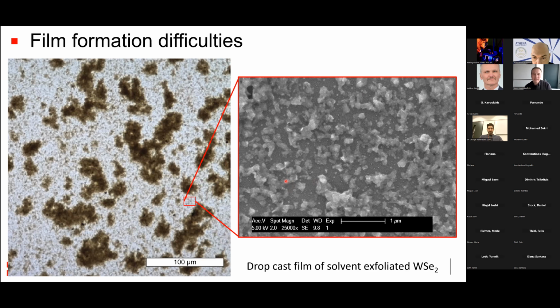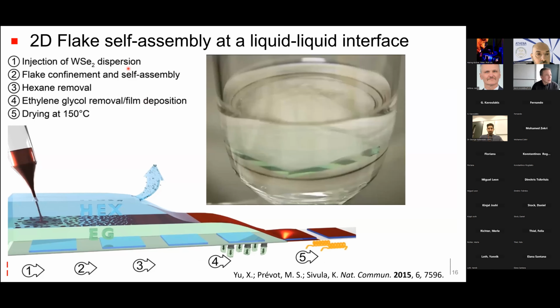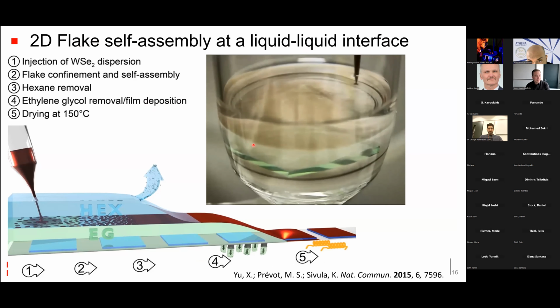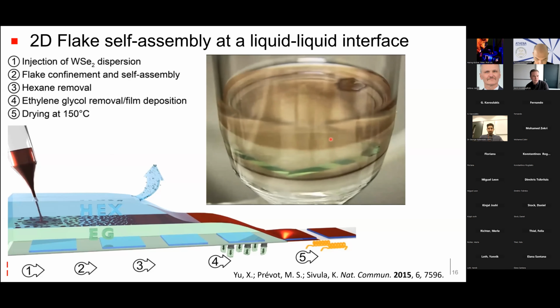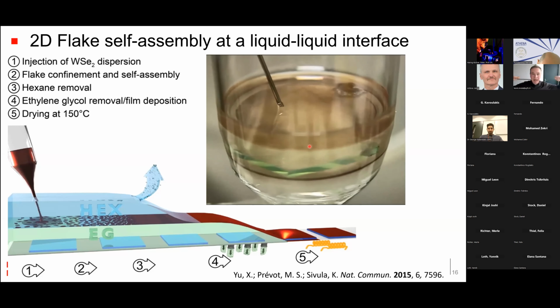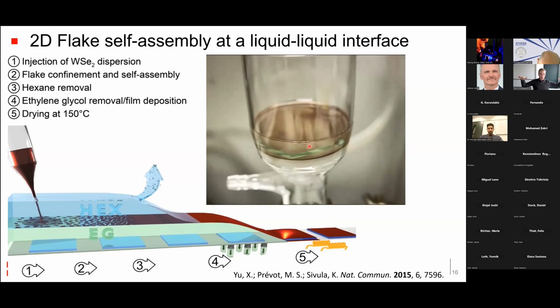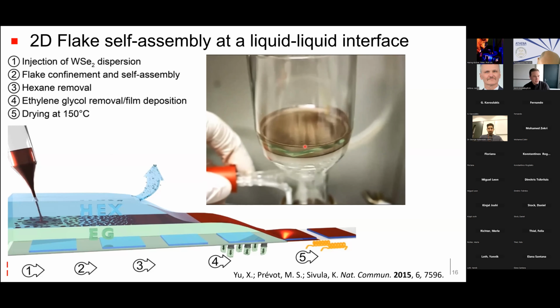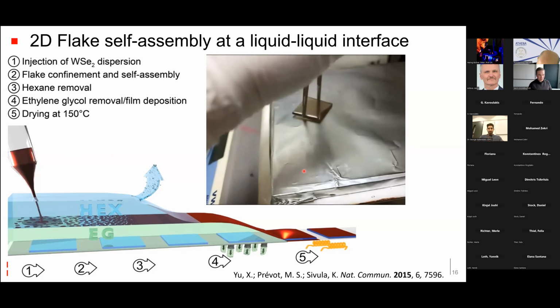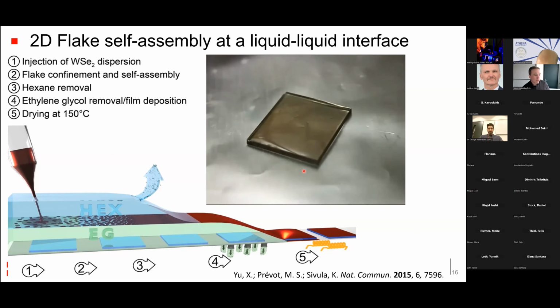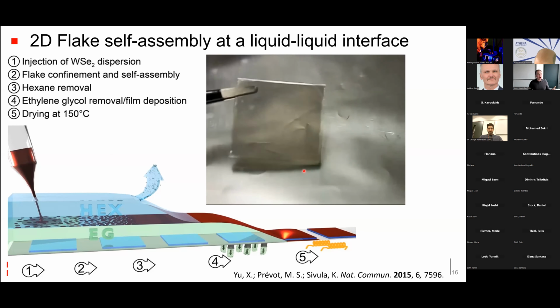But I had a very brilliant PhD student who figured out that we could use flake self-assembly at a liquid-liquid interface. So I'll just show you a video here quickly. We inject the dispersion of the nanoflakes at an interface, for example, of hexane and ethylene glycol. And since our solvent here, NMP, is soluble both in hexane and ethylene glycol, the solvent goes quickly into those phases, leaving the nanoflakes to minimize their energy and align at that liquid-liquid interface quickly. Then we can simply remove the solvents, depositing the film on a substrate that's waiting. A small heating to remove any residual solvent leaves us with a nice film of our nanoflakes of tungsten diselenide.